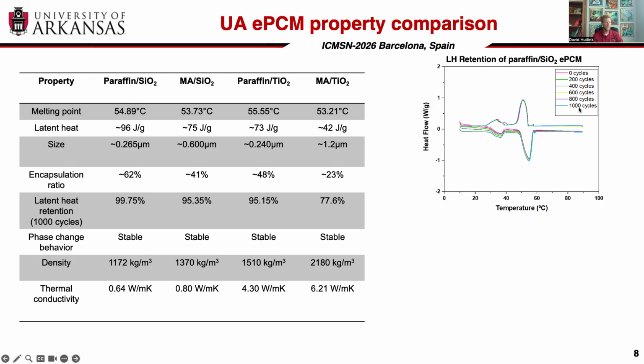As we go through 1,000 melt and resolidification cycles, we notice that we have very little loss in the performance of the materials. And so this is important too for integrating it into a system where you want to have these operating for a long time and maintain stability.